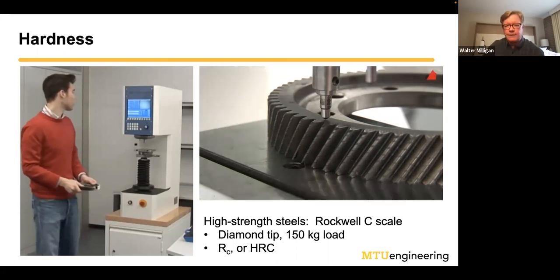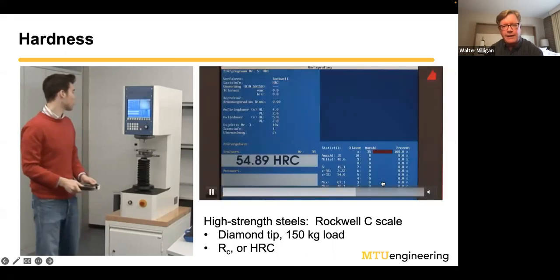So in that, modern testing machines, the Rockwell hardness test is fully, or yeah, we don't need the video on this, but basically it's going to take that diamond tip indenter there and it's going to go down and make an indentation in the metal. I don't know if you can see it going up or down, and then the machine automatically detects the depth of the indentation, and the deeper it goes, the softer the metal is, and it displays the hardness on the screen. It's a very rapid test. You can do this in 30 or 40 seconds. It's non-destructive, so you can actually test your part and then put it in service in some cases.